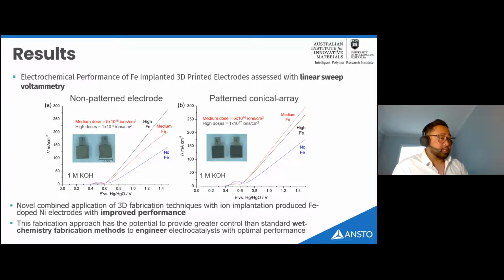So this suggests that the implanted iron has a positive impact to increase the electrocatalytic performance in the water oxidation reaction. But while performance increases with increasing dose in the non-patterned electrode, as you can see on the left, what's interesting is that for the patterned electrode, there's almost a comparable performance observed for both implantation doses. In fact, the medium dose, surprisingly, shows slightly greater improvement than the high iron implantation dose.